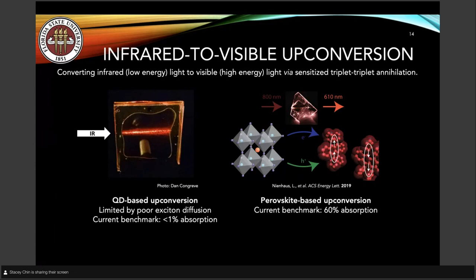And therefore, we could only get less than 1% absorption. And so if your absorption is less than 1%, that also sets an upper limit of any upconversion efficiency to roughly 0.5%. So that's where perovskite-based upconversion comes in. And our current benchmark is about 60% absorption.